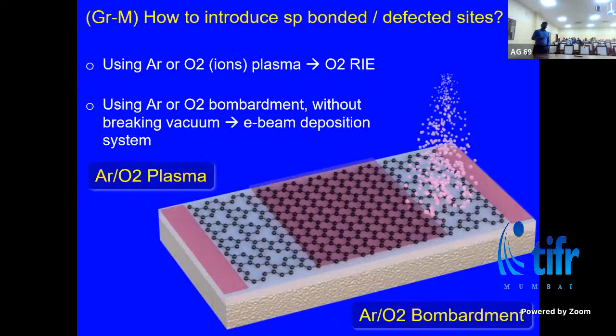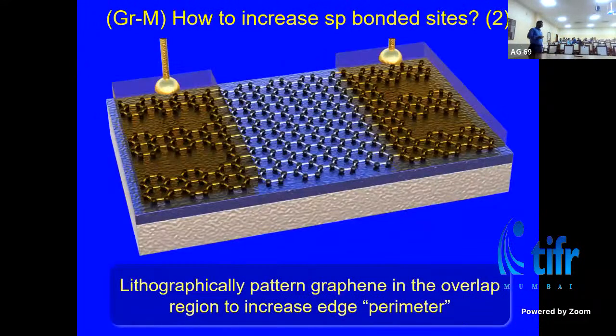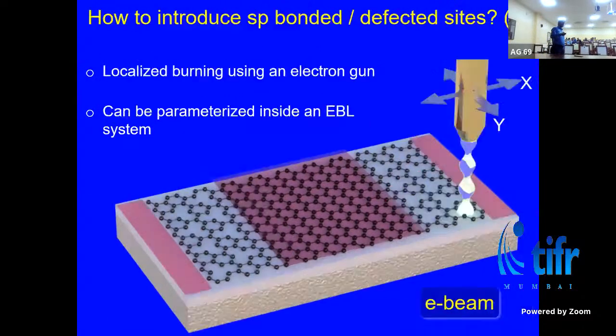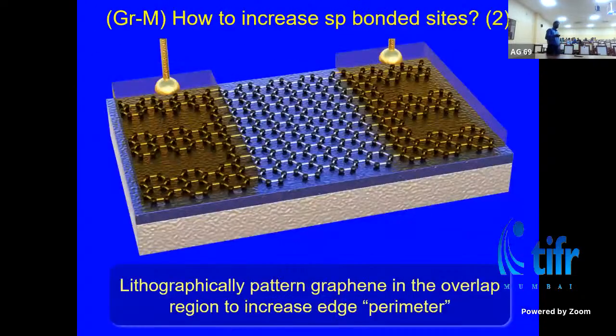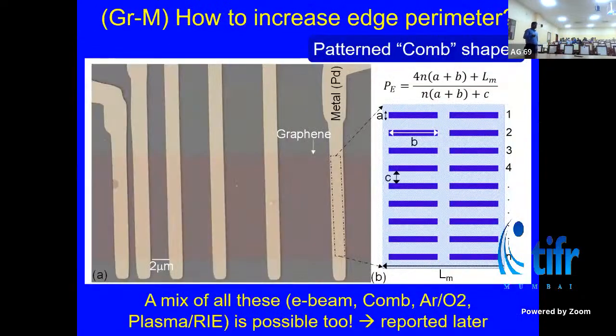So that's one approach. The other approach was you can knock out atoms physically or chemically using argon or oxygen plasma in the contact region, right? The third method is we lithographically pattern these edge regions and create more edge regions, right? So we call this one form, we call this RIE, and this is EB, right? So this is a typical TLM test structure where you have graphene and you have these contact pads on the top.